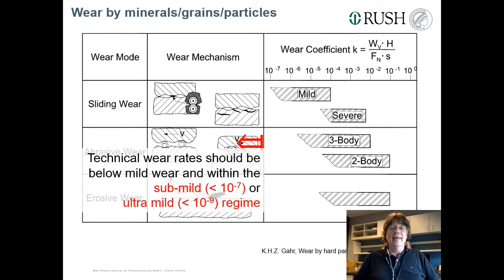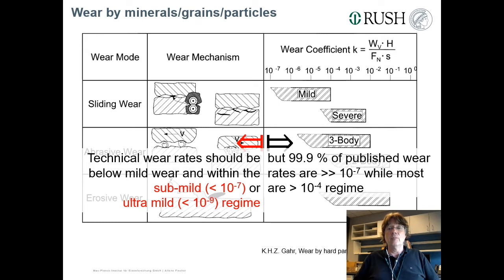The problem is that when it comes to real applications, this K value in the submild or ultra-mild wear regime must be distinctly smaller than 10 to the power of minus 7, and 99.9% of the published wear rates from laboratory tests are much bigger than 10 to the power of minus 7. Most of them are in the range of 10 to the power of minus 4. So you lose roughly 5, 6, or 7 orders of magnitude of lifetime if you do something here, and you don't know whether the mechanisms and sub-mechanisms that contribute to the wear behavior in your laboratory test at these high K values have anything to do with what you aim for in real applications.